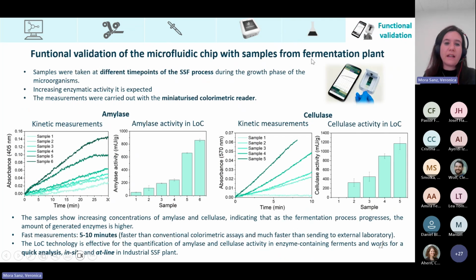Finally, we perform the functional validation of the chip and also the portable reader employing these real samples. The samples were taken at different time points of the solid-state fermentation process during the growth phase of the microorganisms. So we expect to have increasing enzymatic activity in these samples. And of course, the measurements were carried out with the miniaturized colorimetric reader.